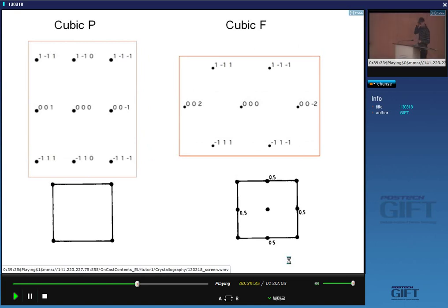This is a case where we are looking at the 110 beam direction. And this is what we had earlier for the cubic P. But we've already said that we do not get 110 reflections here because, look, if this is the 110 plane, we've also got another set of scattering centers in between. So instead of 110, we get 220, and 220 will come at double the spacing here, so it will come somewhere there. Similarly, we do not get 0, 0, 1. We've got 0, 0, 2. So 0, 0, 2 and 2 bar 2, 0 is somewhere there. If I combine these two, then I will get a 2, 2, 2 here and a 1, 1, 1 here.